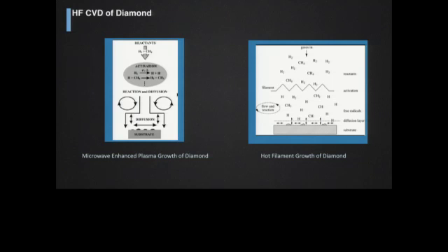So the process of how we do chemical vapor deposition is pretty simple. We have to create these free radicals, and these free radicals then impinge on the surface, where there are a number of nucleation sites, and I'll tell you a way in which we can enhance the nucleation. There's of course a chemical reaction, and we can get the formation of diamond. And there are some things that you can add to the reaction that help facilitate the growth of diamond versus graphene or carbon-based compounds. This is a very similar chemistry for both the microwave enhanced plasma growth technique and the hot filament technique.